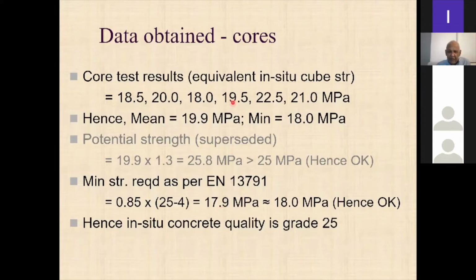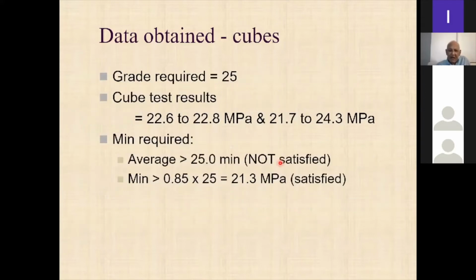So your minimum strength obtained here should be greater than this, and it is just greater than that. Actually, if you round this up, you will get 18. But anyway, the minimum strength requirement is satisfied there. So then you say the in situ quality is grade 25. What I'm trying to say here is that this potential strength also gives similar results to this EN, right? But now people generally don't use this potential strength method.